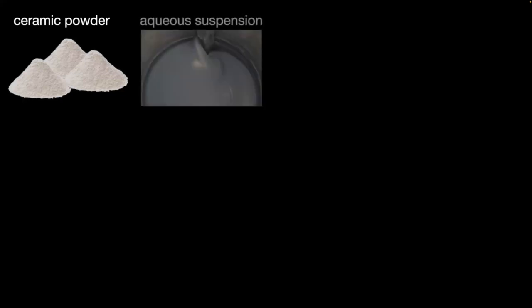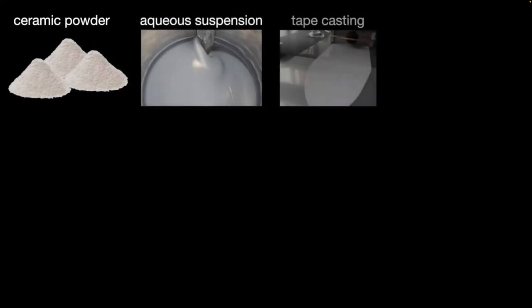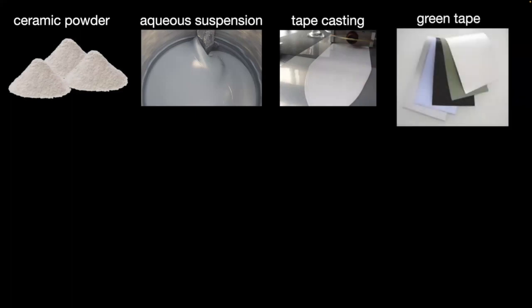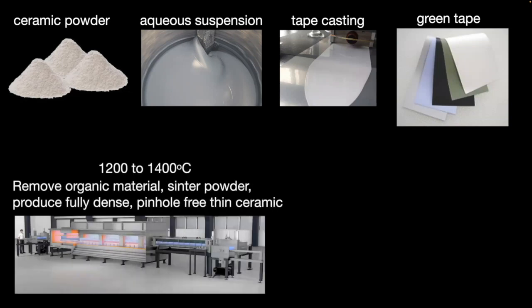So if we look at how you make ceramic membranes, typically, and this is pretty much the way it's done around the world, you start with a ceramic powder, make an aqueous suspension, you tape cast to get a thin tape, and then you've got a green tape. This part of the fabrication of the ceramic component, that's pretty inexpensive, right? And that's how you make a lithium ion cathode or anode too. So this part's trivial. The next part is not.